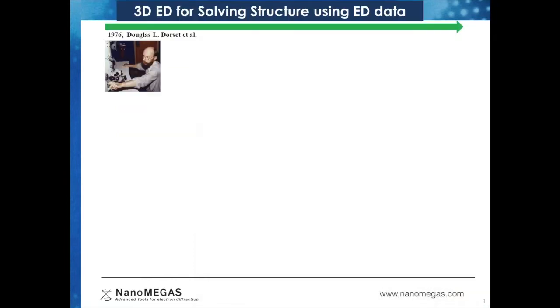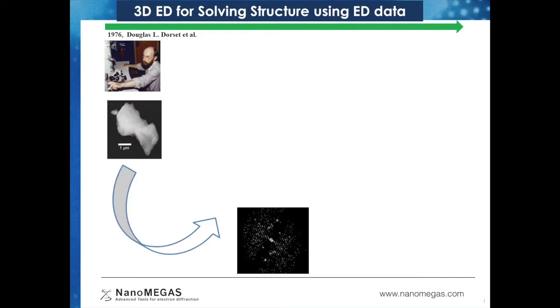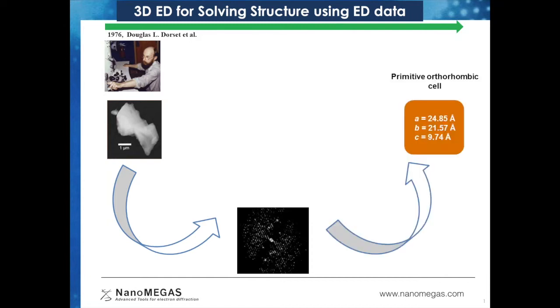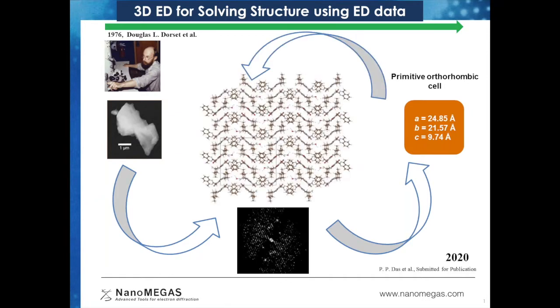So actually, structural analysis by 3D electron diffraction was started in the West in 1976 by an American scientist, Douglas Dorset. And what information can one really obtain using 3D electron diffraction? Let me show you an example from one of our recent works. Once there is a crystal, one can acquire 3D electron diffraction data. From the 3D electron diffraction data, one can determine the unit cell, symmetry, and extract intensities. And once intensity is extracted, one can find all the atomic positions present in the structure, as you can see here.